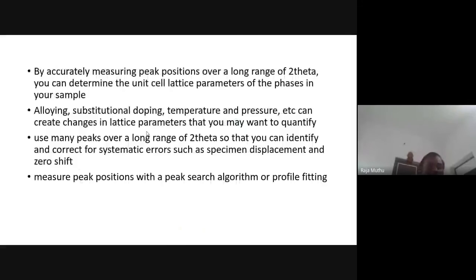By accurately measuring peak positions over a long range of 2 theta, we can determine the unit cell lattice parameters, so alpha, beta, gamma, and a, b, c values. Alloying and substitutional doping, temperature, and pressure can create changes in the lattice parameters that you may want to quantify.